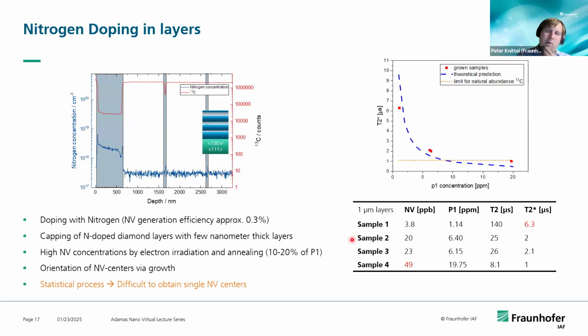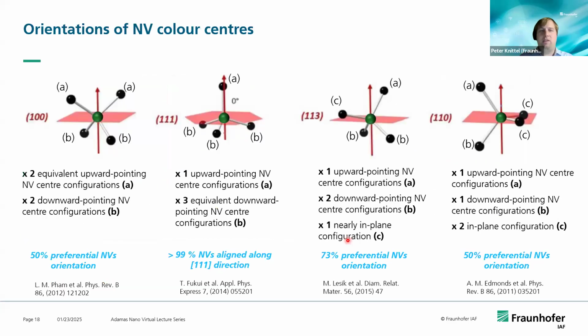But then there is one important thing that is also possible with growth, and this is that you actually can orient the NV center. So the NV center can be located in 4 directions in the diamond, given its cubic crystal lattice, and depending on the orientation of your original crystal, you can get a preferential orientation of these NV centers in certain 1-1-1 directions.